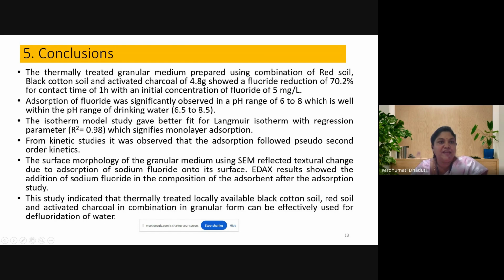to 8.5. And the isotherm model study gave a better fit for Langmuir isotherm with an R-square value of 0.98, which signifies monolayer adsorption. And from the kinetic study, it was observed that the adsorption followed pseudo second order kinetics, and the surface morphology of the granular medium showed textural change due to adsorption of sodium fluoride onto its surface. And also the EDAX results showed the addition of sodium fluoride in the composition of the adsorbent after the adsorption study.